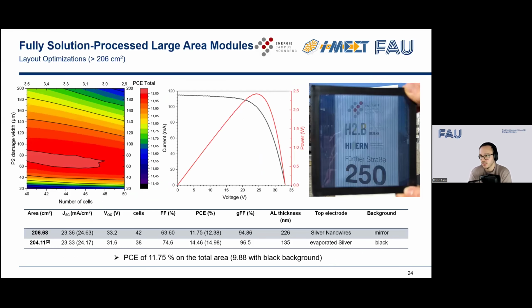And with that, I put it into a CFD simulation, and I found that for a cell width of around 3.4, so that would be 42 cells for the given substrate sizes, we can achieve, according to the simulation, with an input curve of the best cell that we did, more than 12% theoretically with the optimum layout. Of course, there will be some losses too, but we used that layout to fabricate a large area module that is fully solution processed. You have a picture of an example of it on the right-hand side, so it's still transparent. And with the mirror as a background, the champion device achieved a PCE of 11.75% on the total area and over 12% on the active area, which is quite high.